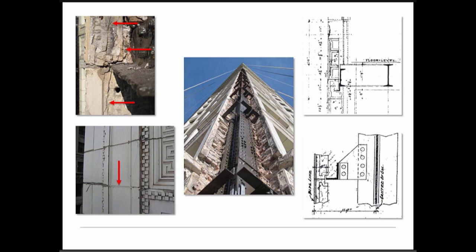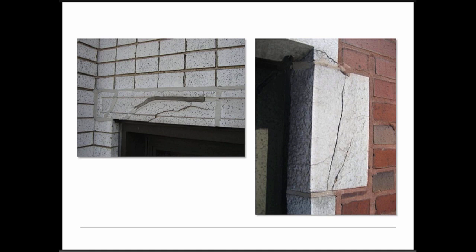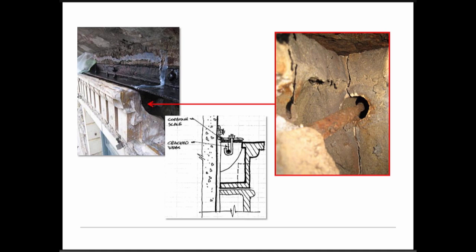Corners of buildings are notorious for steel not continuing around the corner and providing full support, leading to movement issues that can become stacking effects. Corrosion on the angle causes additional distress. In-plane cracking at corners may not be visible from outside. Lintels are also often prone to distress, especially when the lintel goes into the masonry wall without being separated from the jamb or pier units.